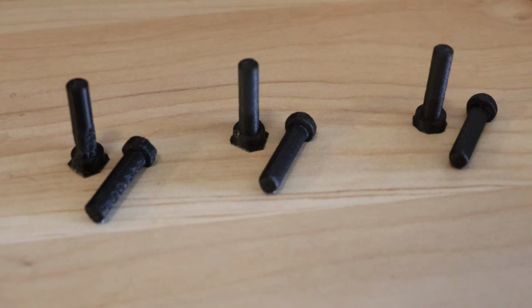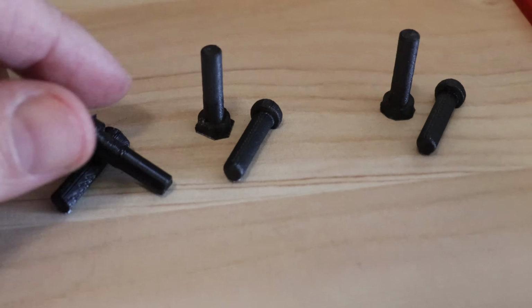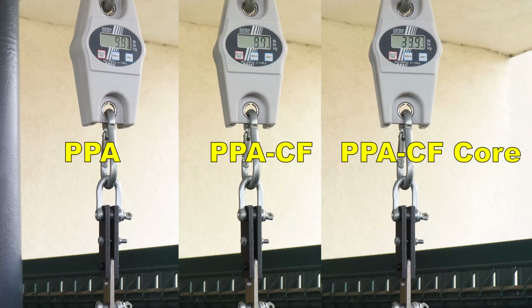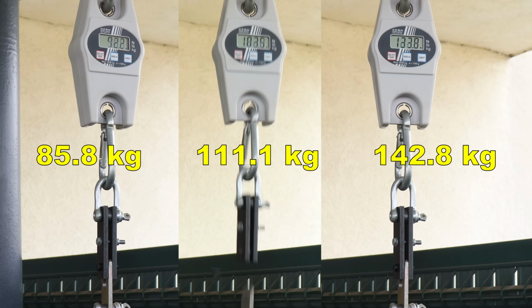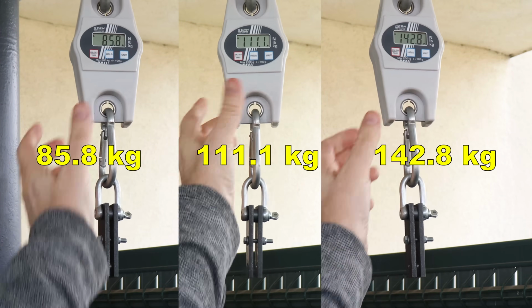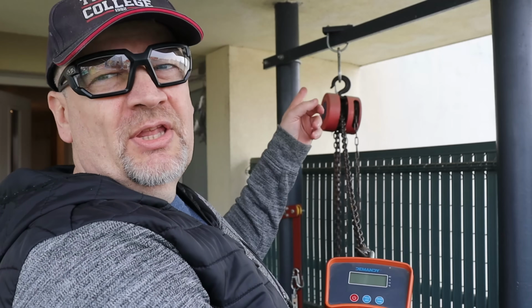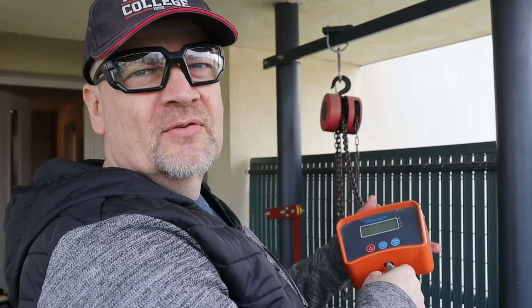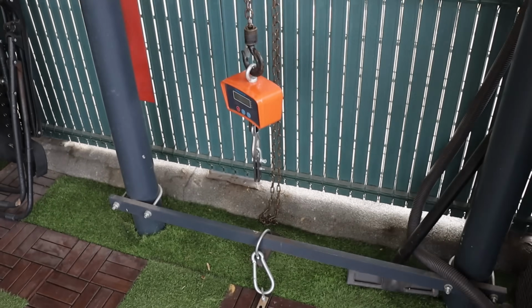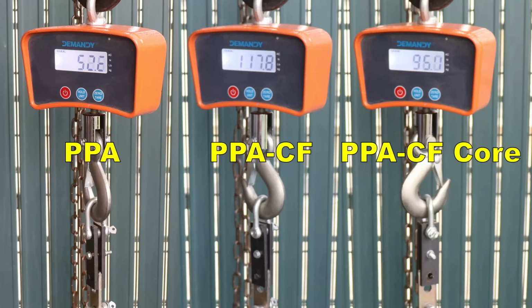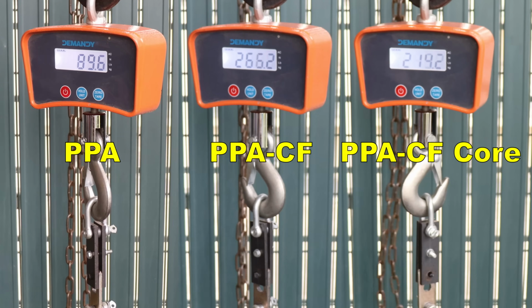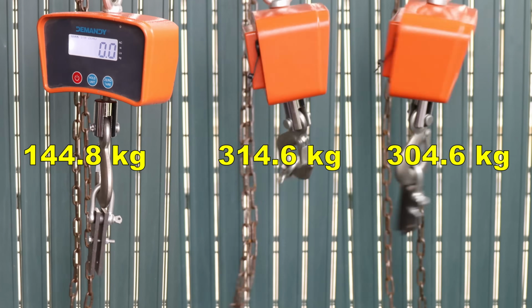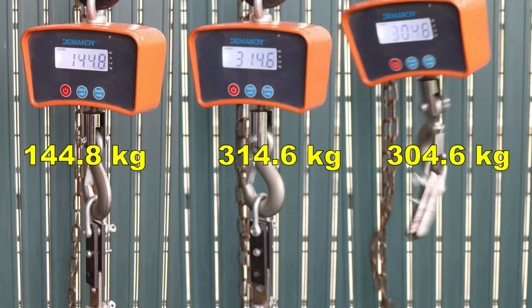And now the shear test, and I'm starting with vertically printed test objects. And in this case the layer adhesion is very important, and no surprises here, the core version was the strongest. And now switching to the chain hoist and this crane scale, because I know that here I'm expecting much bigger loads. With this equipment I can measure up to 500 kilograms, only this scale don't show the peak of one measuring, so I have to analyze the footage digitally, and here I have the freeze frame.